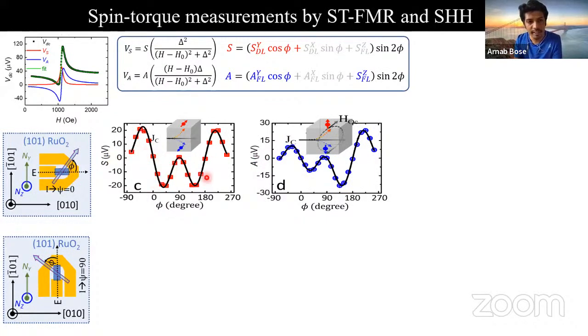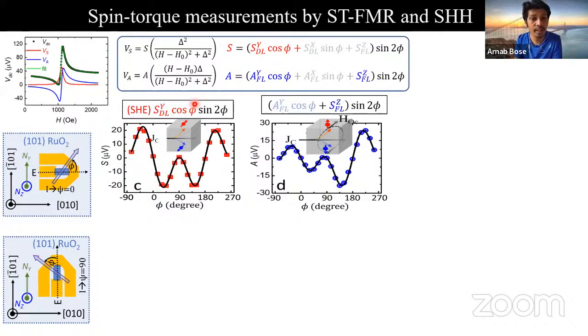The angular dependence of S can be fit using cos phi sin 2 phi, which is the standard spin Hall effect contribution. But for the antisymmetric component, on top of the Oersted field, we have an extra contribution resulting in sin 2 phi angular dependence. That indicates that we have extraordinary torques generated by the out of plane spins flowing in the out of plane direction.